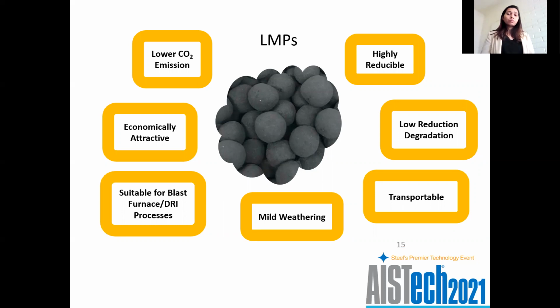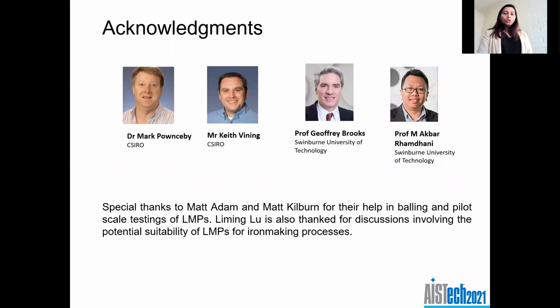So far we have seen mild weathering of these LMPs, but again we need to do more experiments in this area. But the results from the pilot testing and the cost and emission analysis suggest that the LMPs are potential feedstock for blast furnace iron making, and also, in terms of properties like strength and reducibility, they are suitable for the DRI operations as well. However, the chemistry needs to be adjusted for the DRI process, obviously.